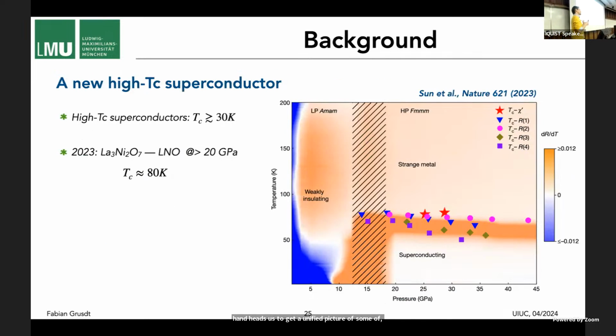Okay, and the story I want to tell you, before I talk about all this complicated 2D Hubbard physics, I want to start with a slightly different and, conceptually, I think, simpler variant, which is another type of superconductor. Basically, it's a bilayer nickelate compound. People put pressure on it last year, and what they found is if you increase pressure, you basically get a structural phase transition of this material, and you get into a superconducting regime here. Okay, and the TC is something like 80 Kelvin, so clearly it's a quote-unquote new high-temperature superconductor, right?